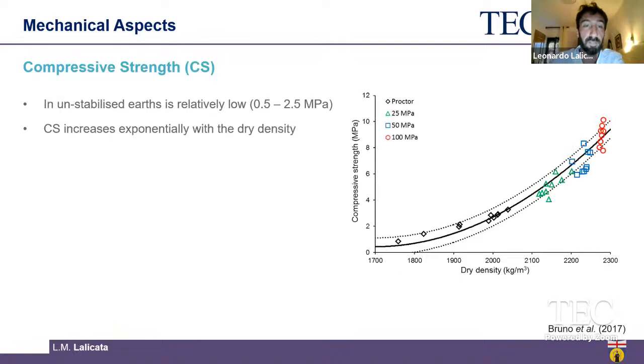But another beneficial effect of increasing the density of our samples, of our bricks, is that we increase the compressive strength exponentially. As you can see, for normal Proctor-compacted earthen materials, the compressive strength is about 0.5 to 2.5 megapascal. But if you increase the compaction energy, so increase the dry density, you get up to 10 megapascal of compressive strength, which is more than suitable for construction purposes.